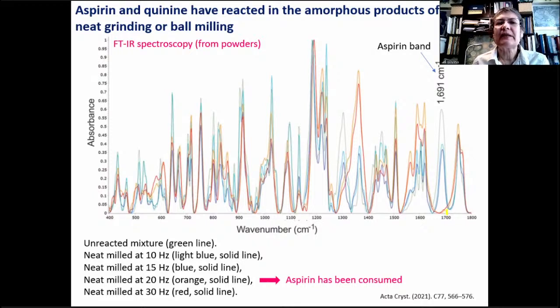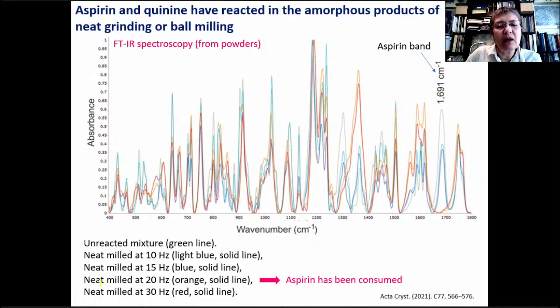Infrared spectroscopy showed that the products ball milled at 20 hertz and 30 hertz, which are these orange and red lines there, did not have a band at 1691 centimeters to the minus 1, which corresponds to aspirin. So aspirin has been consumed and a total mechanochemical reaction has occurred, although the products were not crystalline by powder diffraction.